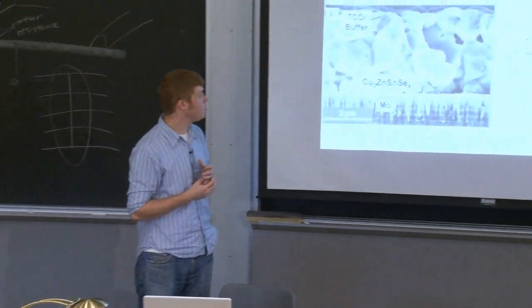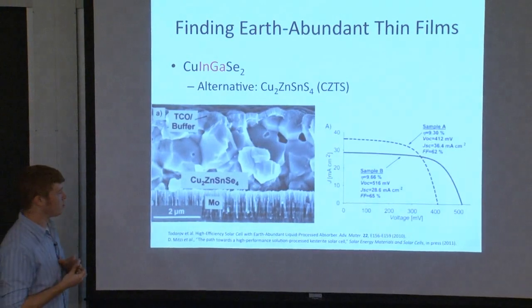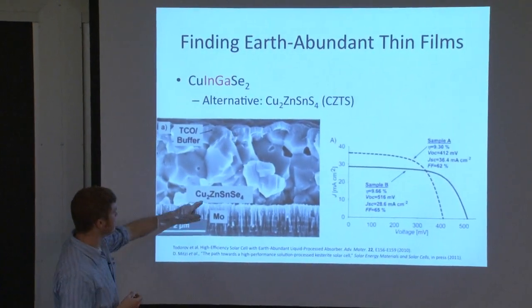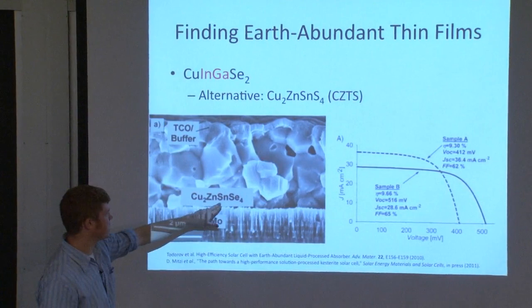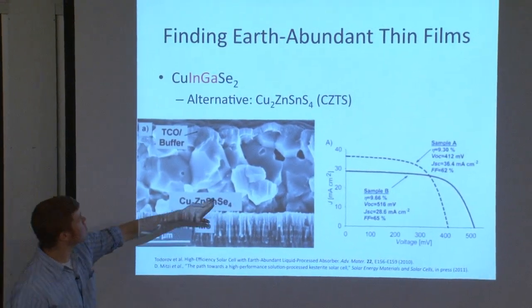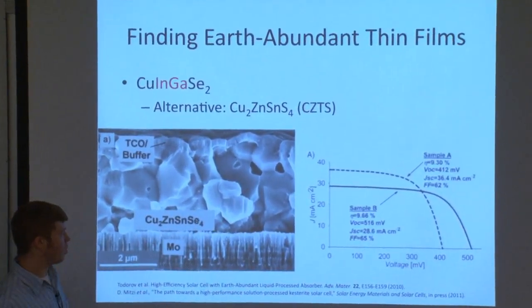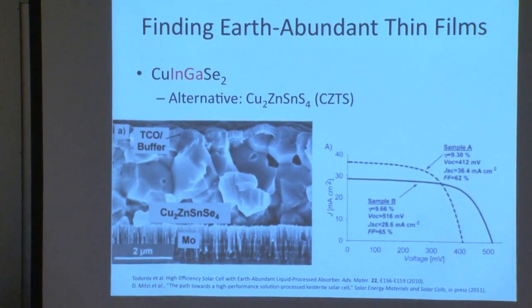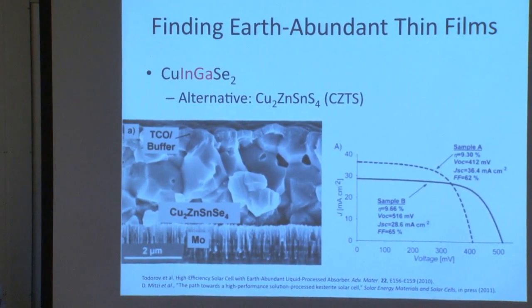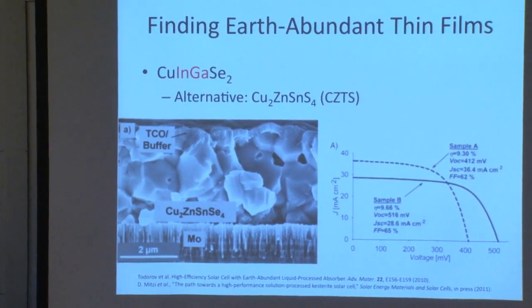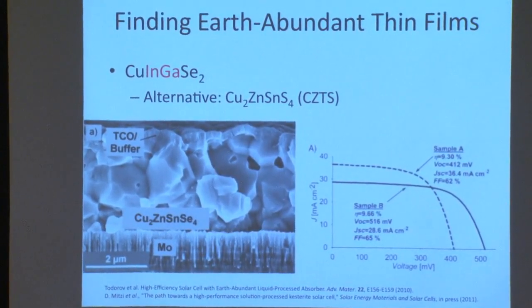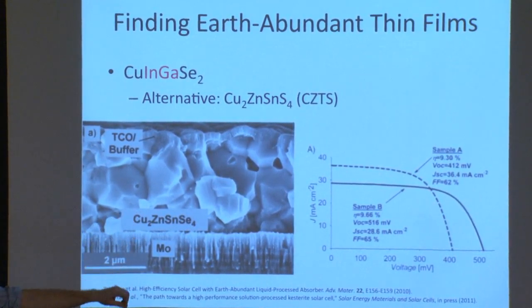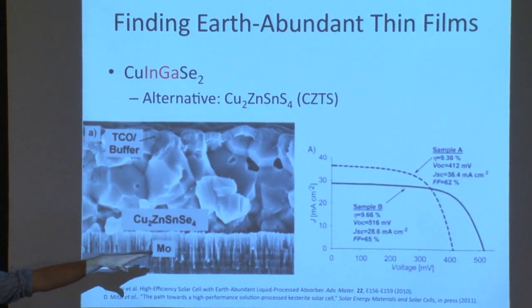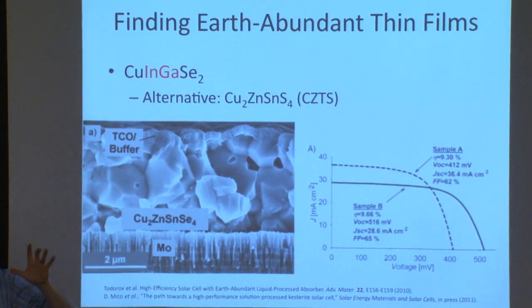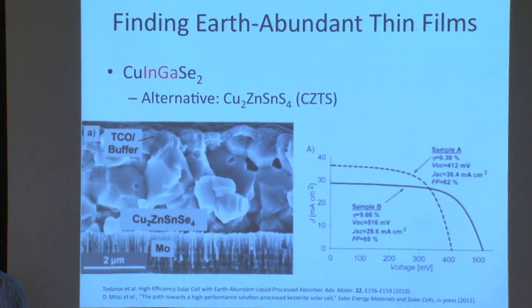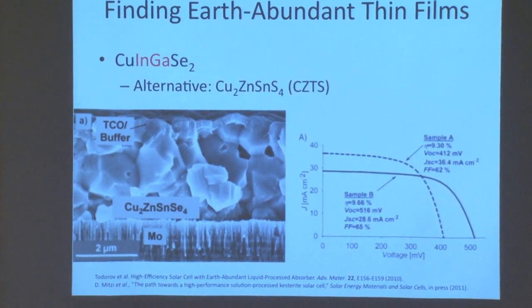Thank you. So what people have been working on is looking at replacements. This is CZTS, so it's copper, zinc, tin, sometimes sulfide. This is selenide. But they are also working on replacing the selenium with sulfur, something a little more earth abundant. And this was done at IBM. It was pretty remarkable, actually, because within a very, very short period of time, they were able to get efficiencies of around 9.6%, which for a fledgling material is incredible. I'll get to why that was so incredible in a second.